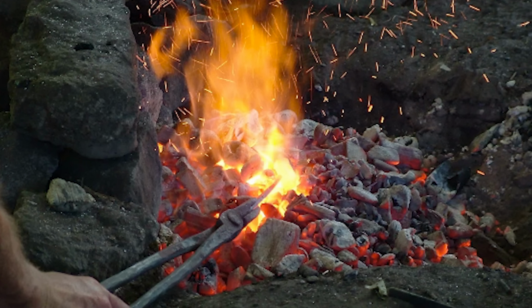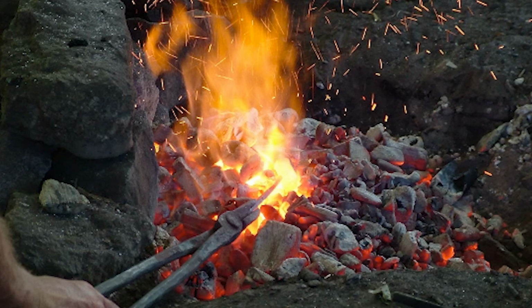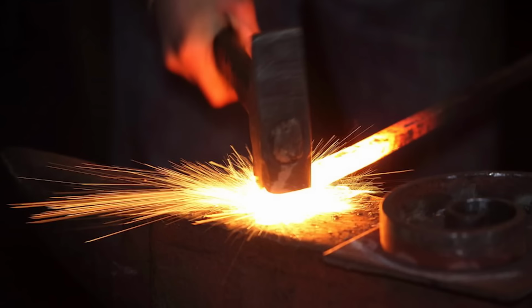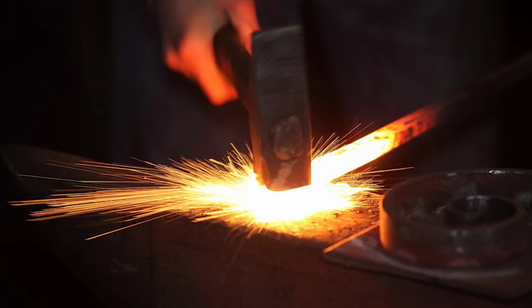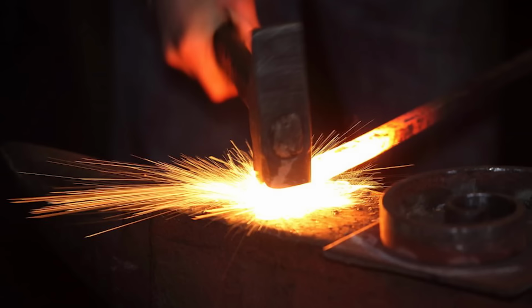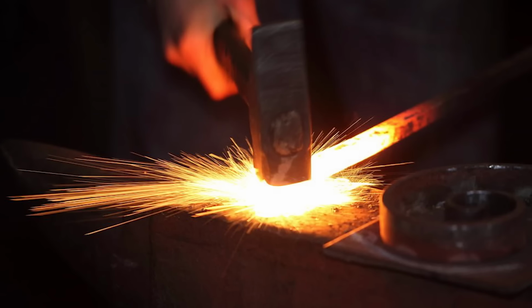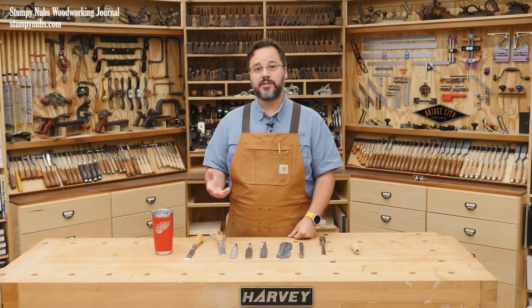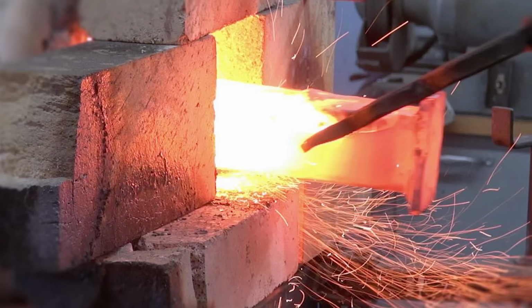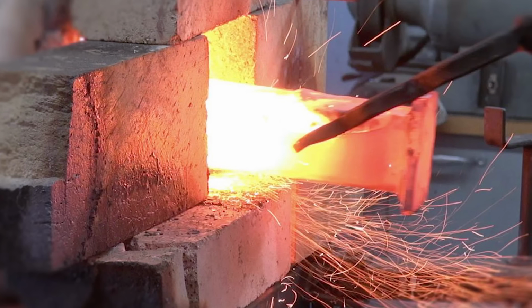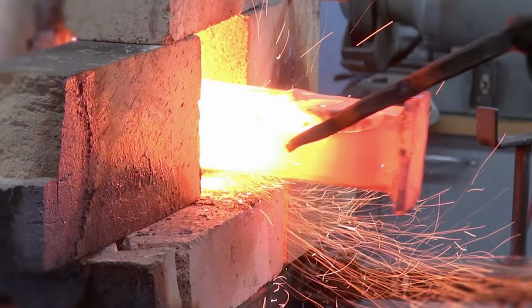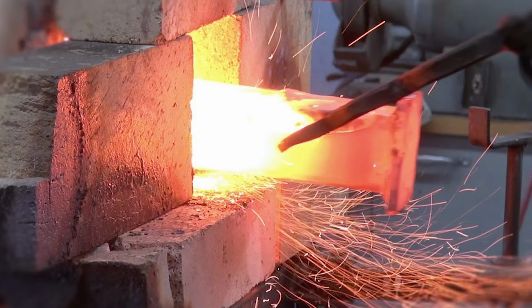Now, a very skilled smith might be able to leave just enough carbon in the iron to make a decent steel, but finding the right balance was a very difficult and inconsistent process. Eventually, someone figured out that you could put some carbon back in if you put some wrought iron and some charcoal in a sealed box and you cook them together for a long time in a very hot furnace.